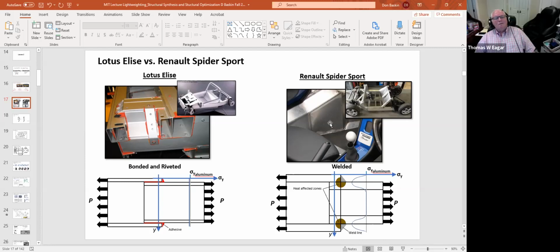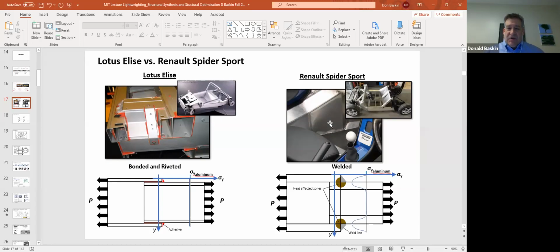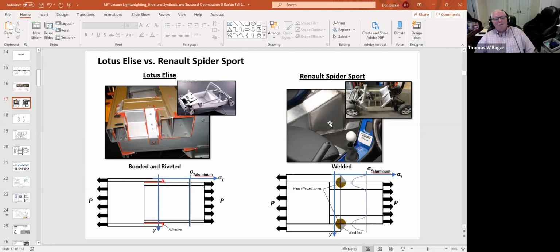Whereas the Lotus, because they glued everything together, used a non-thermal process. All the microstructure of the aluminum extrusions stayed the way they were from the get-go. They were able to use much thinner wall material, much thinner wall extrusions. And that's where the weight difference came from. It's the effect of this heat affected zone not being in the Lotus, but being in the Renault.